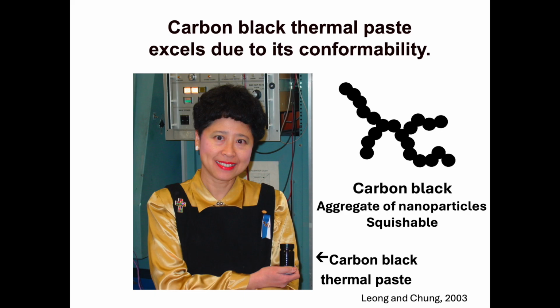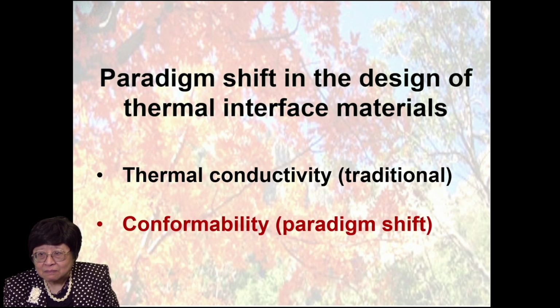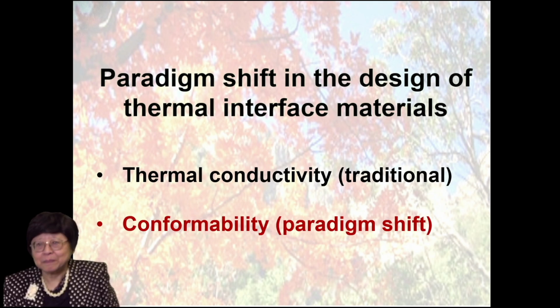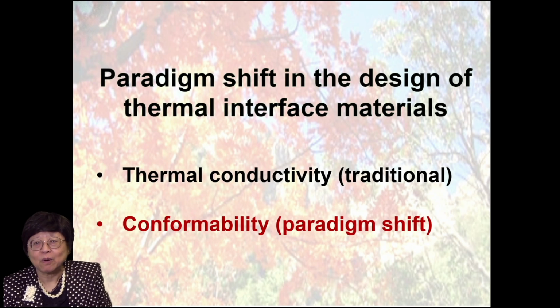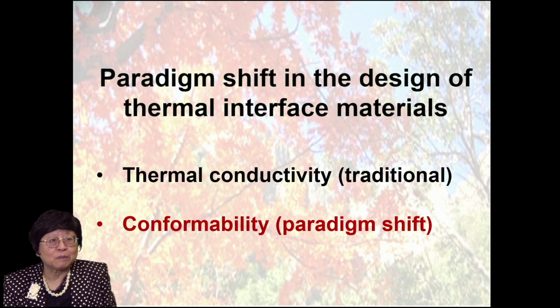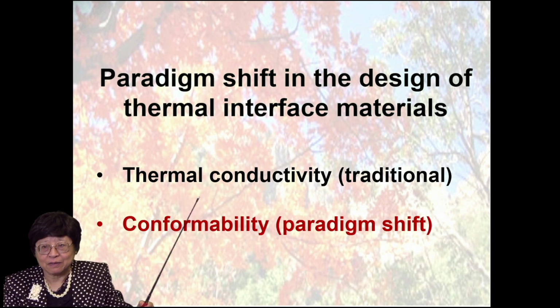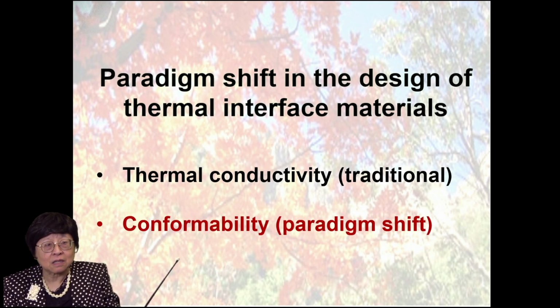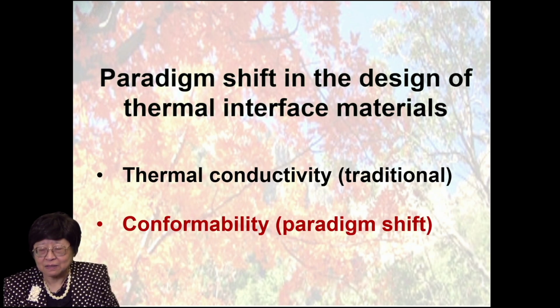Now, carbon black has a nanostructure involving aggregates of nanoparticles, and it's like little filaments sticking out like an octopus, and it's just van der Waals forces linking these nanoparticles. And so when you compress it just a little bit, it's going to squish. It's squishable. And because of the squishability, it's very conformable, even in the solid state. So I put forth this new concept and therefore brought forth a paradigm shift in the design of thermal interface material. Used to be just thermal conductivity. Now there's a paradigm shift so that the conformability is just as important.